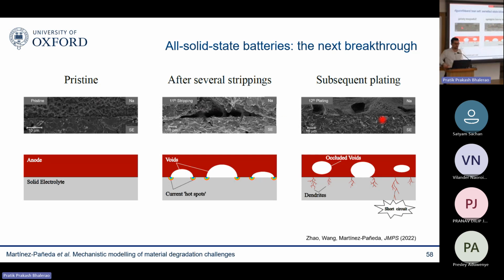You deposit lithium here, and therefore you see that those voids shrink in size, and even get occluded from the electrochemistry you see here. And those voids are critical because at the edges of those voids, you're going to have localized regions with very high current densities. And in those very high current densities, you're going to have the nucleation and growth of dendrites. So we need a model that is able to capture how those voids evolve in time and how those current hotspots will be formed to determine whether we reach a critical value of current or not.